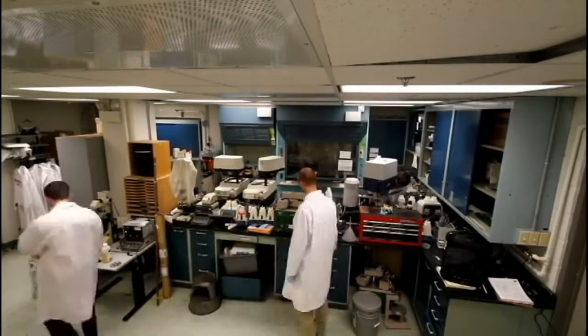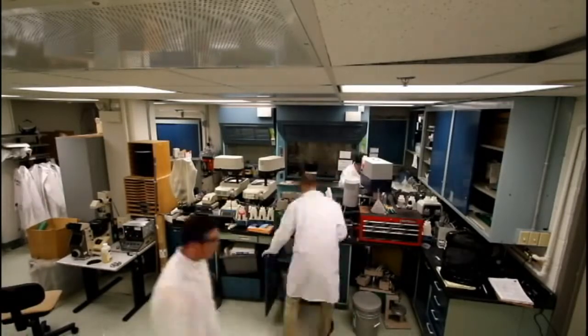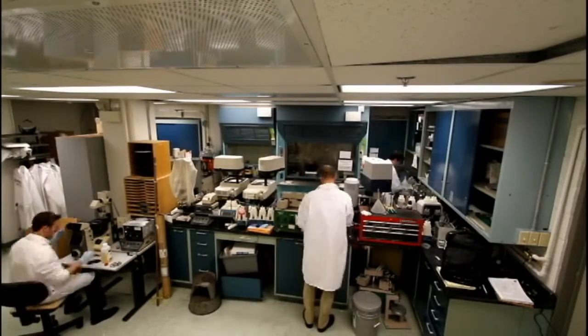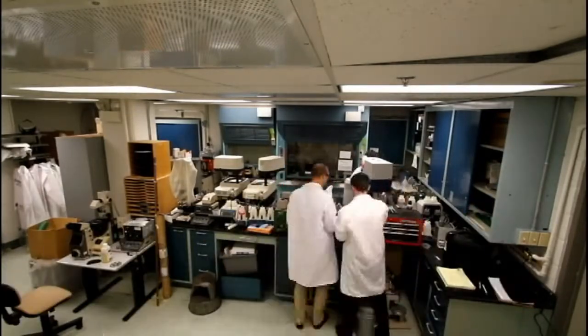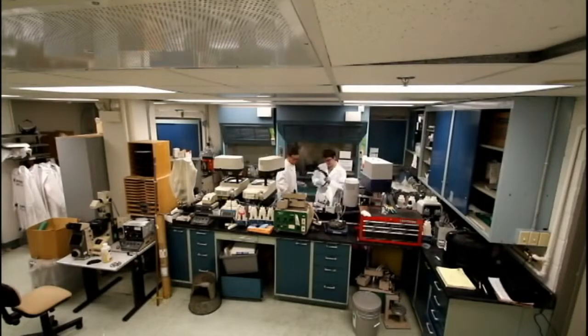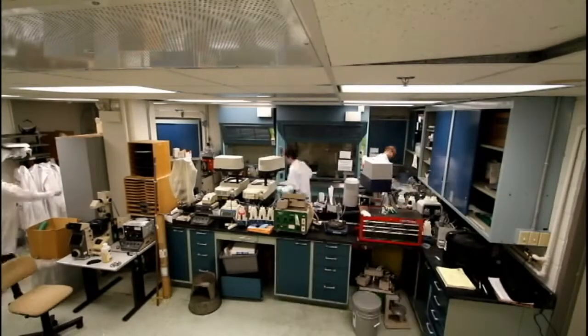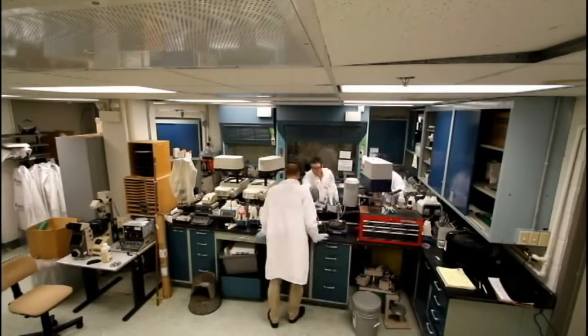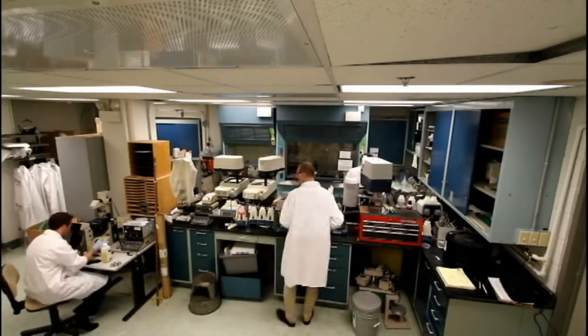This summer, we are examining broached specimens of NASA's low-solvus, high-refractory alloy that have been cycled to the point of failure, and have already seen preliminary evidence of cold work and phase segregation. Following hardness testing, we will etch these samples to expose the microstructure, i.e. grain and phase distribution, in order to correlate changes in hardness with changes in phase.